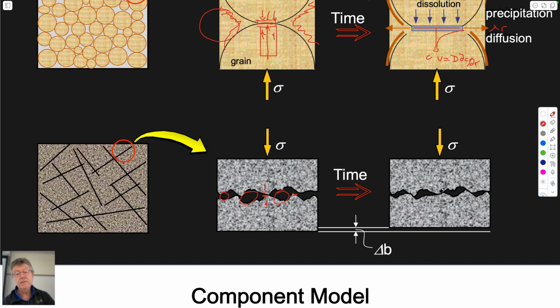The issue with a fracture is that it has a stress acting on it. So as soon as you dissolve material here, the upper fracture will follow with it and it will close. And so it's this overall difference between the top and bottom of these parts of the fracture which will close as it grows together. So it needs the influence of stress to drive that behavior. And of course in our sample we have a constant stress applied on the edges of the sample in the core holder. And of course in a reservoir you'd also have those stresses acting in the system.